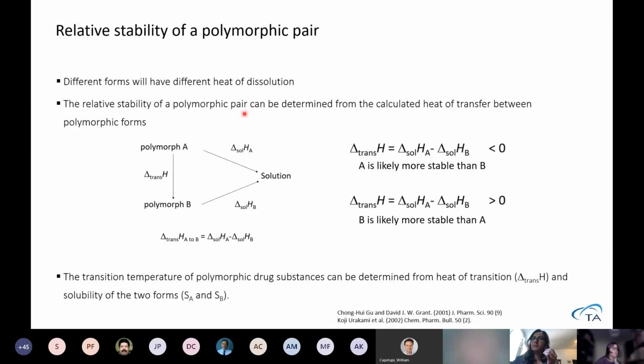So we can measure the heat of dissolution of polymorph A. We can measure the heat of dissolution of polymorph B, and by Hess's law, we can then subtract these from each other to get the transformation enthalpy. So we can take different paths, and we get the enthalpy of transformation between them. And then, depending on if it's an exothermic or endothermic reaction, we can say that A is more stable than B, or B is likely more stable than A.